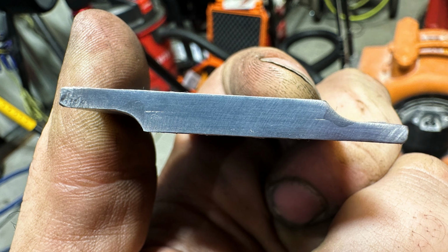So to put these differences in real world perspective, look at this picture. The weld on the right was done where I was focusing more heat on the top edge of this 1/8 inch plate, and it more or less melted it down into the bottom plate. And the weld on the left is what happened when I focused that arc on the joint. Both of these have filler material added to them. Now the weld on the left is a little bit concave, and that's very typical of TIG welding in general. You have to push enough metal to bring that out to a 45-degree angle.